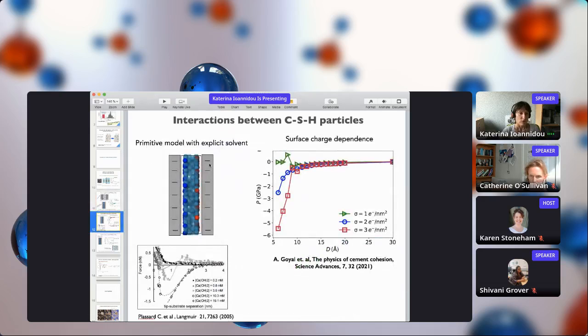So to give you a bit more information on this model, we did the same calculation with different surface charges. As we increase the surface charge, we see that at some point we reach a cohesion on the order of 6 gigapascals, which is the order we find in cement.